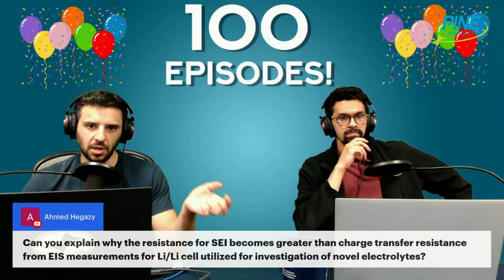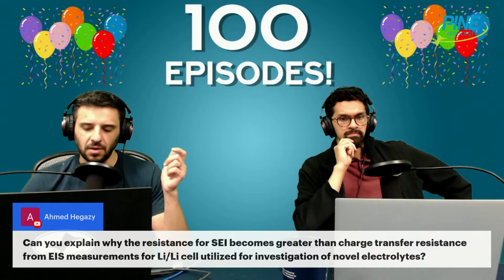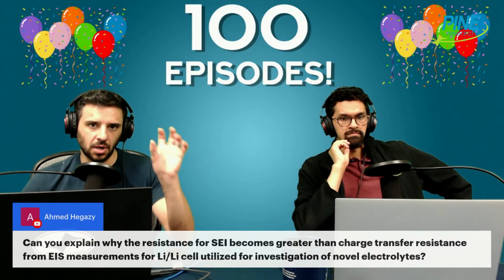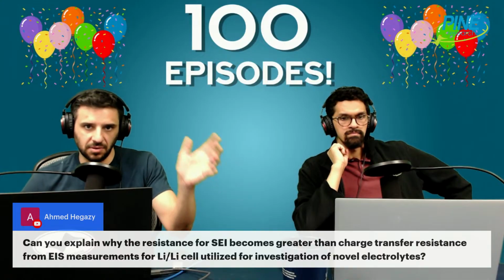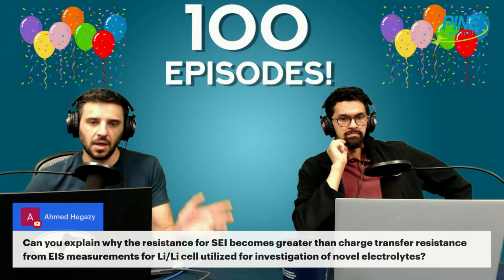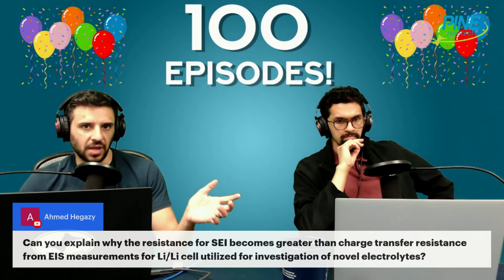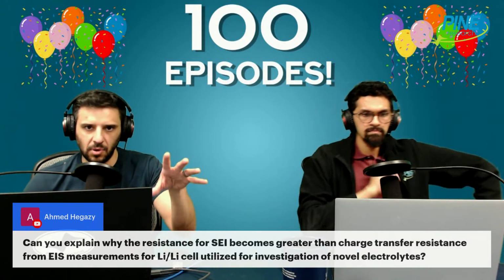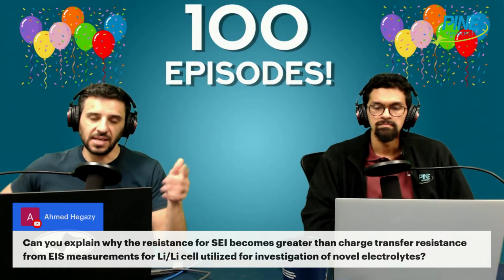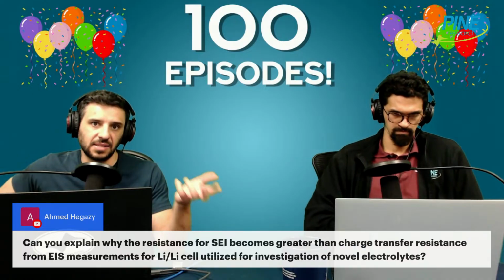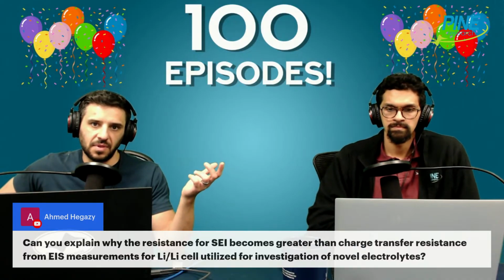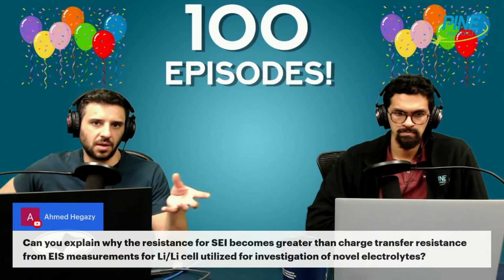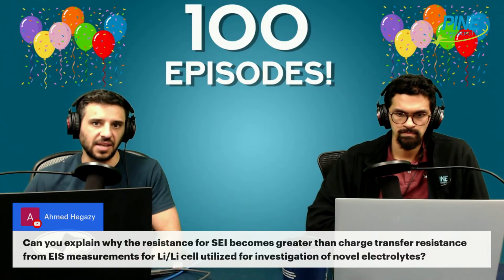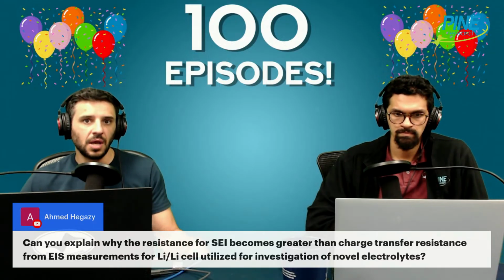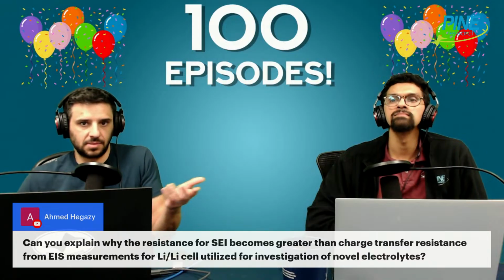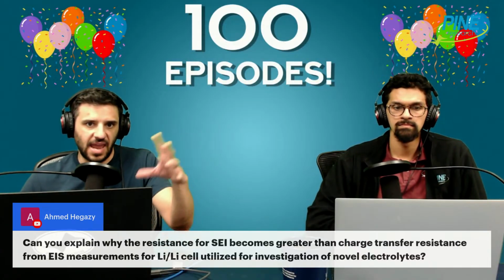And lithium ions, whether they're intercalating or it's a conversion reaction or an alloying reaction, are joining into the anode, the material, the carbon, the silicon, whatever it is, right? But another way that they can stick or join on the anode side, and it could be both, but I'm just describing it in the anode context, is that they can join into the SEI itself. I don't know precisely how, or if people have imaged or quantified this per se, but in some sense, there's secondary storage in the SEI that we know can occur. And so lithium plus is, in some way, hanging out in the SEI.